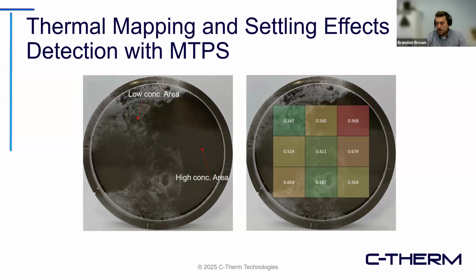If you know heat capacity and density of a sample, I think Adam talked about this earlier, it's possible to calculate thermal conductivity from effusivity, which in this case was the goal of this application, but we also have calibrations for many material classes. Here, you can visually see the areas of high and low concentration of conductive filler. The black areas are the high concentration. When we measured the sample over a grid pattern, the correlation between the high filler concentration and the high thermal conductivity is clear, and this is a good example of bad filler dispersion.